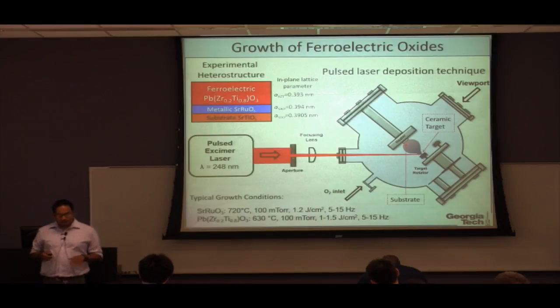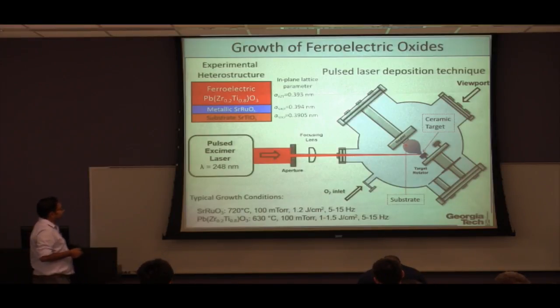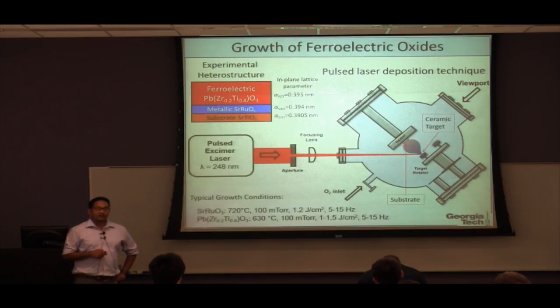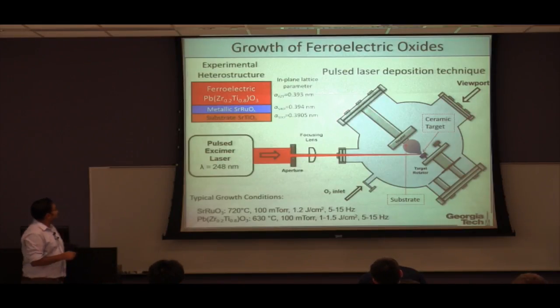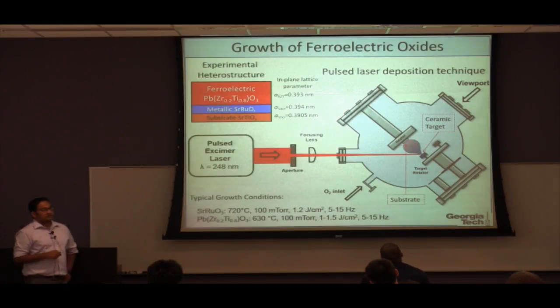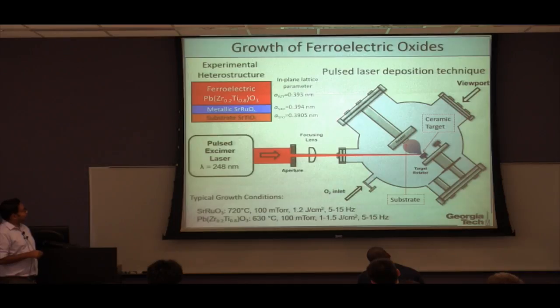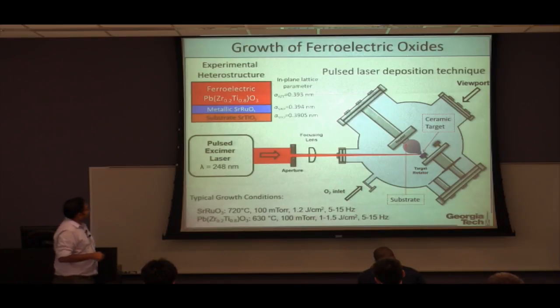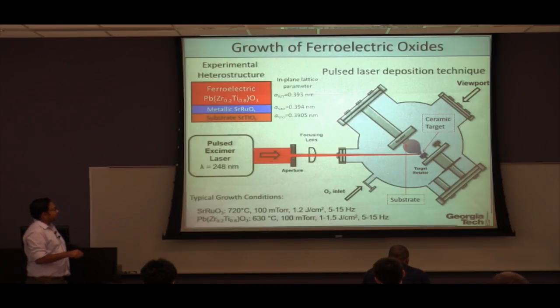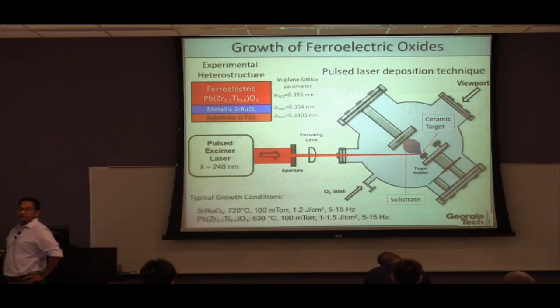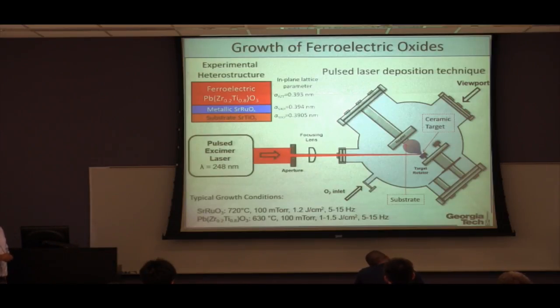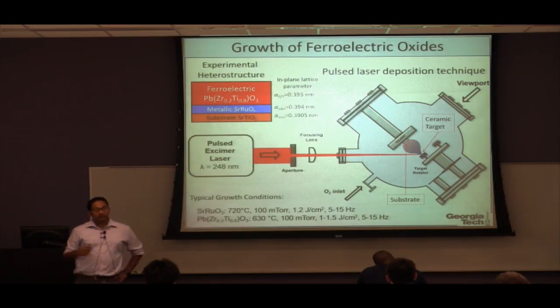All right. So before we go into the details, this is how we measured, this is how we grew our materials. For ferroelectric materials, we took lead zirconate titanate as our ferroelectric material on top of strontium ruthenate metal electrodes. The technique by which we deposited these materials is called pulsed laser deposition, where you have a vacuum chamber and a laser comes in and hits a target material and creates a plasma of this material. Then we have a substrate on the other side on a heater, and this is how the material gets deposited on the substrate.